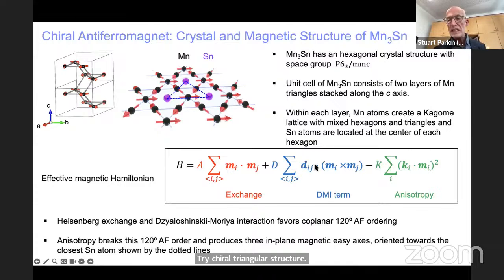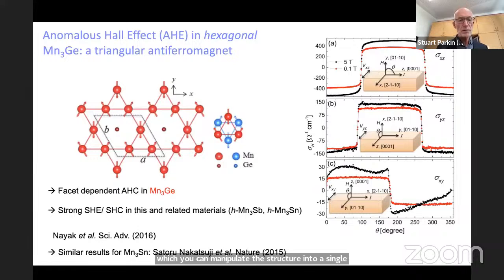Very interesting structure. There's also weak anisotropy favoring magnetization on the manganese atoms pointing towards the tin. This leads to a slightly small net magnetic moment with which you can manipulate the structure into a single antiferromagnetic domain state. And it was predicted by two groups, by Allan MacDonald's group and Claudia Felser and Jürgen Kübler, that these types of systems should display large anomalous Hall effects. In other words, look like a ferromagnet. I don't want to discuss this in detail. We've been exploring, in particular, how we could switch the antiferromagnetic state using spin orbit torques, and we've demonstrated that it's dominated by heating. Nevertheless, we can switch the state to a great extent in these materials using spin orbit torques, but only when there's a lot of heating. We don't care about that.